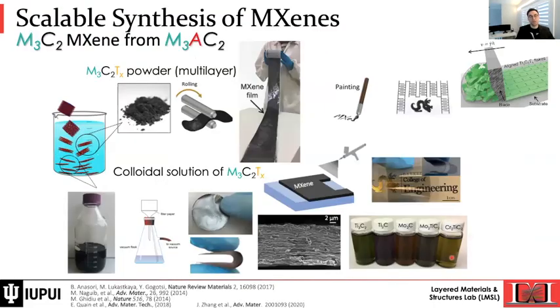MXenes are among the ones in the 2D world that can be scaled up. And that's very important because the synthesis is a top-down method. It's not a growth mechanism. By just making the reactor container larger and having more starting precursor mass, we can make a larger quantity of MXene film, MXene solution, or MXene powder. And they behave like a clay, so water or other cations can easily integrate into the MXene structure.